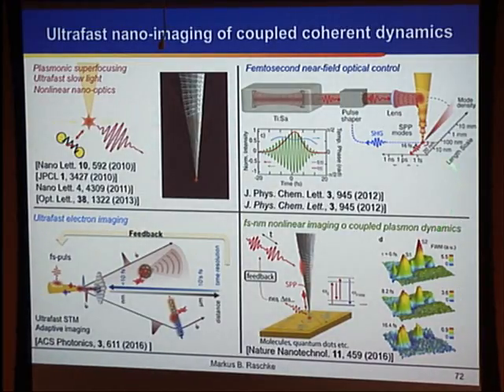And we can also use this strongly confined field at the apex as an electron source. The strong nonlinear interaction, which we're using for four-wave mixing, also gives rise to the nonlinear emission of electrons. So we can generate short electron pulses. This is work in collaboration with groups in Berlin, which we then use for point projection imaging. And we just got 40 femtosecond time resolution in pump-probe with electron imaging.